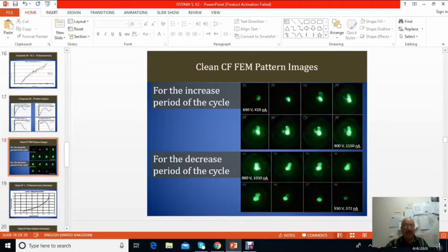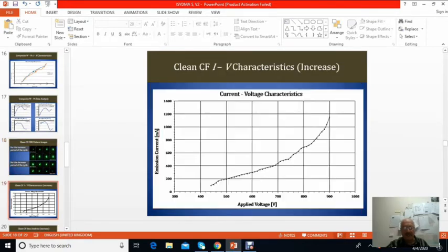characteristic. Now we come to the pattern images, clean carbon fiber film pattern images. This is for the increasing cycle. So it starts at 690 volts, 410 nanoamperes, and we end up with 900 volts, 1150 nanoamperes. Then this is the decrease cycle, and when it is reduced here, it is 550 volts for 372 nanoamperes. It's very close and repeatable results. So in a bit, we can compare other coating effects.